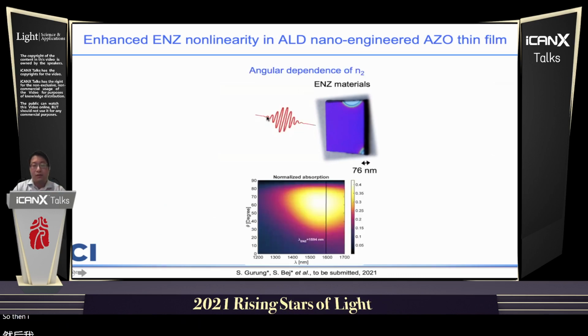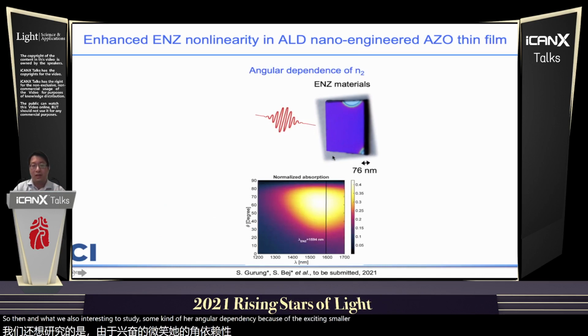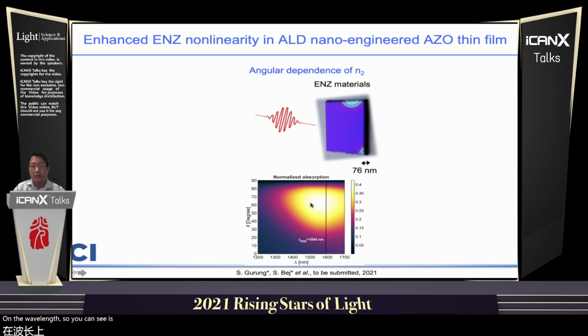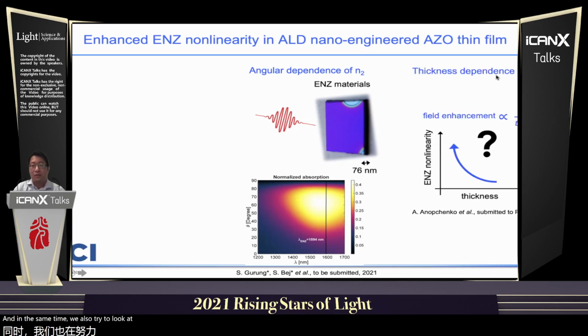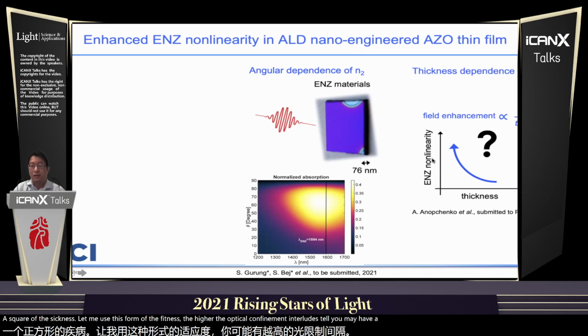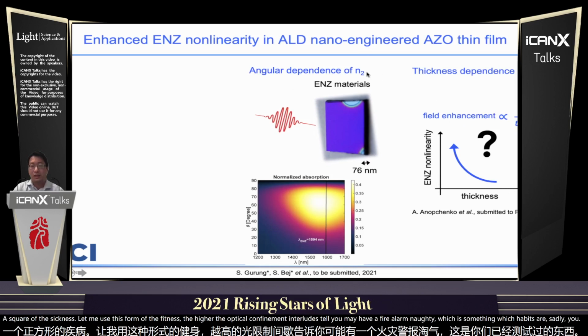So then what we are also interested in studying is some kind of angular dependency, because to excite this mode, as I say, it really depends on the angle of excitation or the wavelength. So you can see at a certain angle and wavelength, you can excite this mode more efficiently. At the same time, we also try to look at, for example, the thickness dependence as well, because there are some reports showing that the optical field confinement is inversely proportional to the square of the thickness. So that means the smaller the thickness, the higher the optical confinement. As a result, you may have a higher nonlinearity. Which is something we try to study using this ALD fabricated ENZ thin film.